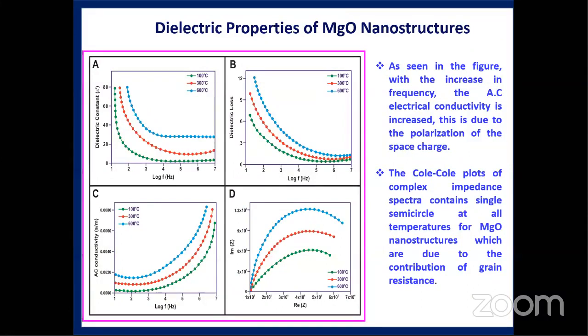And then we performed the electrical property study of the magnesium oxide nanostructure. We did dielectric constant, dielectric loss, AC conductivity, and Cole-Cole plot. You can see this is a very good, quite interesting dielectric property of the MgO nanostructure. Dielectric constant decreases with increasing frequency, and dielectric constant increases with increasing temperature. You can see here the dielectric constant increases with increasing temperature, and there is a high dielectric constant at lower frequency and a low dielectric constant at higher frequencies.